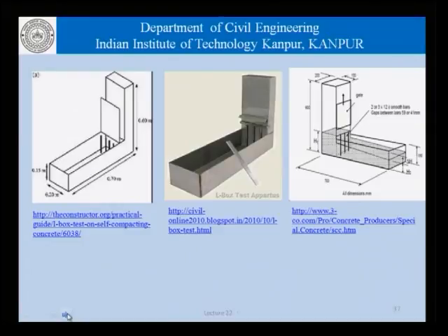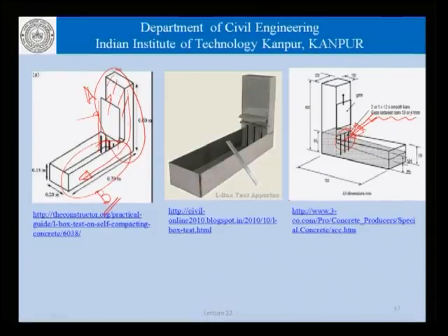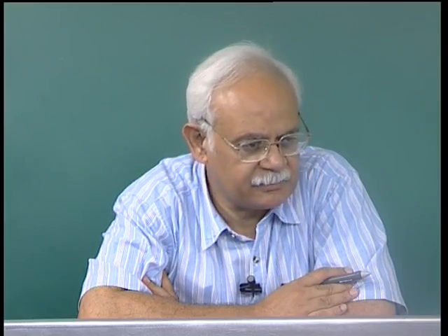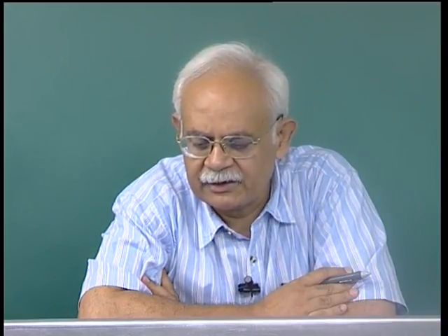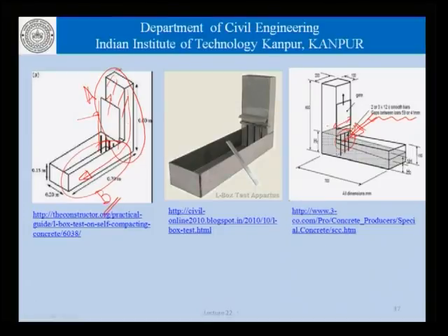Now, this test here has an L box, that is, there is a box here which is, let us say, A, and another portion here which is, let us say, B, and we fill the concrete in A. There is this gate which is closed, and once we lift this gate, the concrete from the block A flows into block B. Now, this flow from block A to block B is restricted by the presence of these pipes or reinforcing bars or any such arrangement that we may choose to use. Some of the standards have standardized the kind of obstruction that can be used in the form of pipes of different diameters or in the form of reinforcing bars of different diameters, in a manner that the space here is divided into different open spaces.